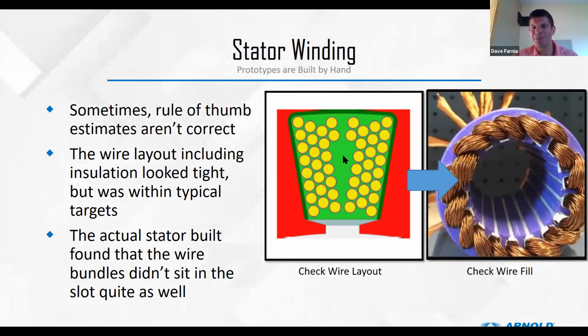And so after that, we went through and started doing 3D prints. We are going to 3D print a stack, do a sample or test insert of the wire, make sure everything goes in correctly, and then hopefully eliminate the potential of getting to the finished stack and not being able to get all the strands in. I should also mention, even with these 3D printed stators, there's flex. Steel versus plastic, plastic is a lot more forgiving. So we typically try to take that into consideration as well when we're doing these sample winds.